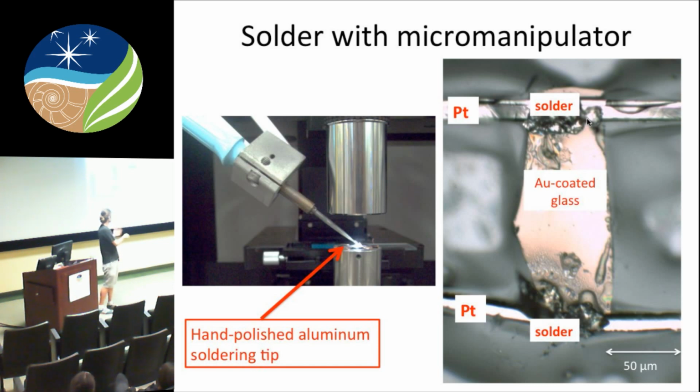And now I think this is a great electrical setup, because the resistance of these leads is less than an ohm, maybe 0.2 ohm, 0.1 ohm. The resistance of this is 22 ohms, so all the power will be deposited at the center of the diamond cell.